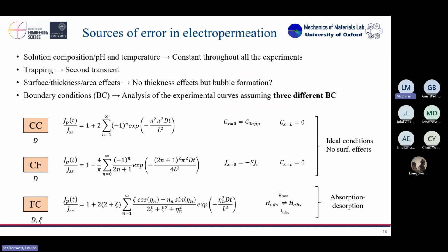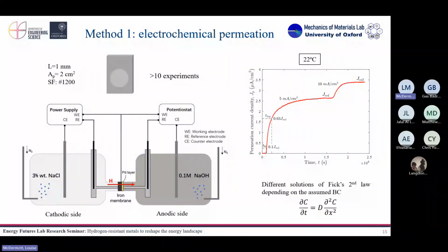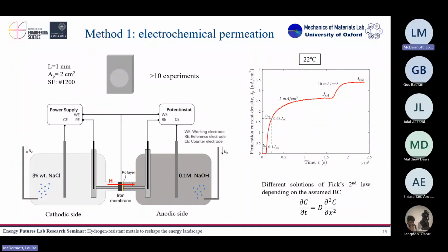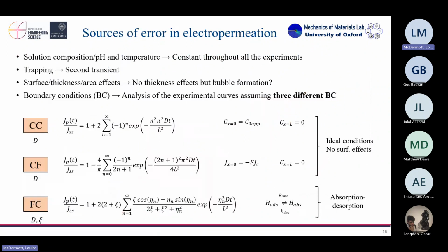Then I started to think about what other things could be providing scattering in my permeation results, or less reliability. One of them is that I have an electrochemical process, so I have a solution with a pH and a temperature. Even though I try to do everything the same all the time, we are not machines, so you have some variability there. Then you can have surface effects, because when you do permeation, you produce hydrogen and you have a lot of bubbling on the surface where you are producing hydrogen. That can reduce the effective area that you are permeating. You can have effects of the thickness. It's not the same doing permeation on a 20 micrometer thick membrane as on a 3 millimeter thick membrane. So all those things are going to increase the scattering that I have between experiments.